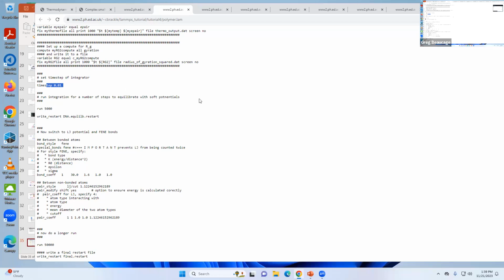Then after that, you would plot out Rg versus time, see if it reaches NL squared, plot temperature versus time, see if it reaches a fixed value, plot density versus time, pressure versus time. Everything should go to a flat number. If it doesn't, then you have to go more than 50,000, and then you go to the Ohio supercomputer. Like I want to do 1,000,000.